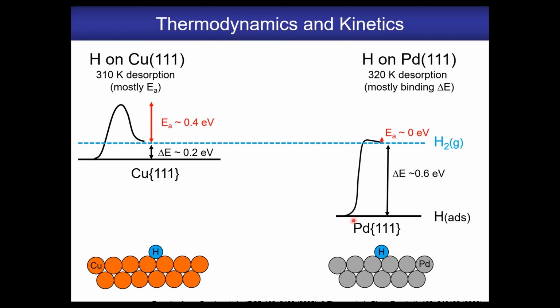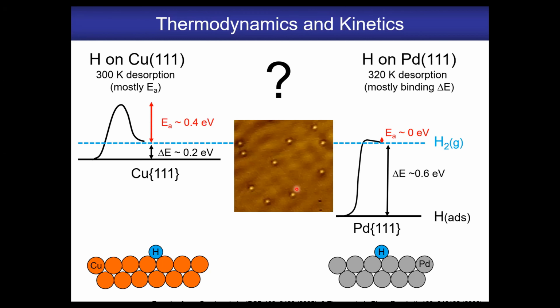So the question is, what do you have when you have just single palladium atoms? And just to make a note about the temperature programmed desorption, the reason they both desorb at 300 Kelvin is that to basically recombine the hydrogen atoms on the palladium takes this amount of energy, about 300 Kelvin. And then microscopic reversibility says that on copper, you have to come back over that dissociation barrier to desorb. And again, that energy is about 300 Kelvin equivalent in a desorption experiment. So the question is, what does the energy landscape look like when you have just single palladium atoms?